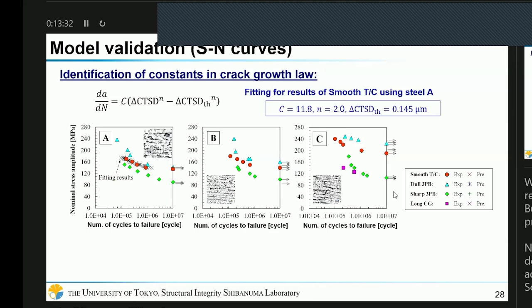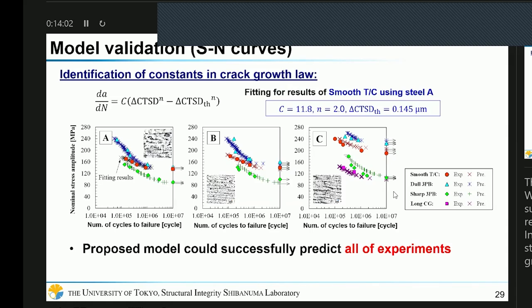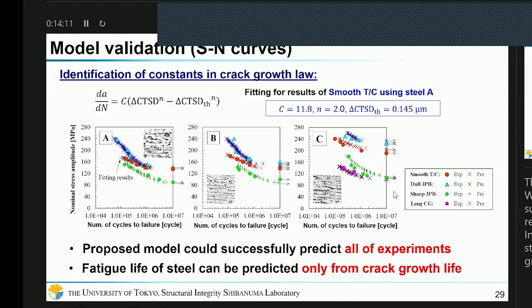But we have 9 SN curves other than these data plots. So we try to predict these SN curves using the same parameter setting. And these are the results. So we can see that the proposed model could successfully predict all of the experiments. And these results indicate that the fatigue life of steel can be predicted only from crack growth life.